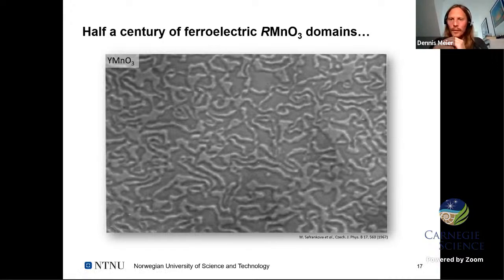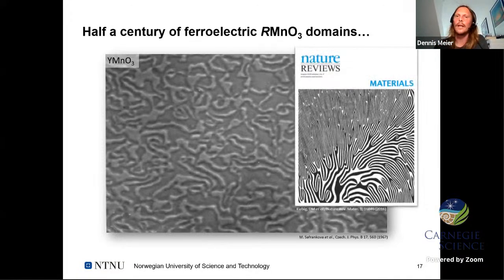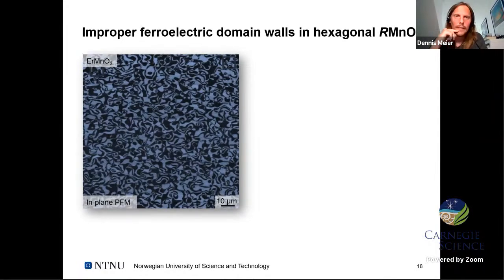It doesn't look like poor quality. If you look at the year when this image was taken, 1967, you see that this is quite some time ago. So these domain structures and their specific appearance is nothing new. Here, optically, they were already imaged some time ago, but only recently people really got interested in these because high resolution imaging allowed us to resolve these 6-fold meeting points of the domain structures, which you can see all over the image, to look more into the domain wall physics and all the interesting things that are happening in this improper ferroelectric. So this is now another image of the ferroelectric domain structure, now with piezo response force microscopy.